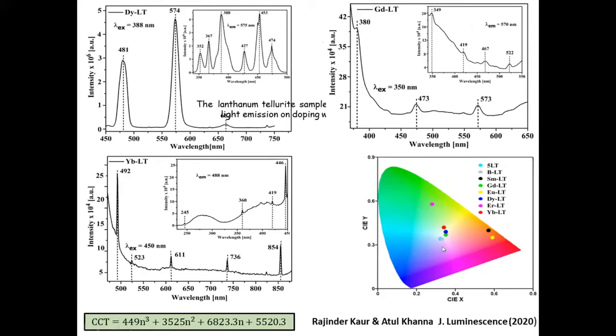So you see the emission of blue light, green and red light from the samples containing ytterbium. And of course, the erbium doped samples emit mostly in the green part of the electromagnetic spectrum. These are some of the PL curves for the dysprosium doped sample. This is for the ytterbium lanthanum tellurite sample.